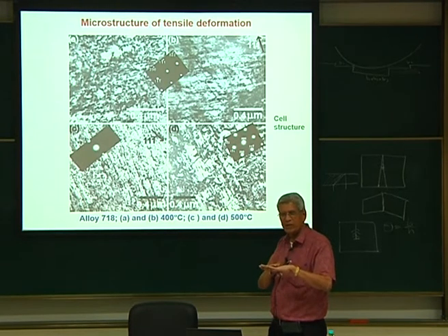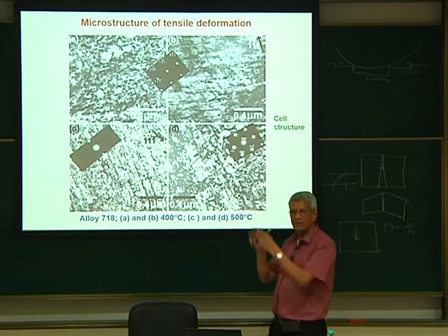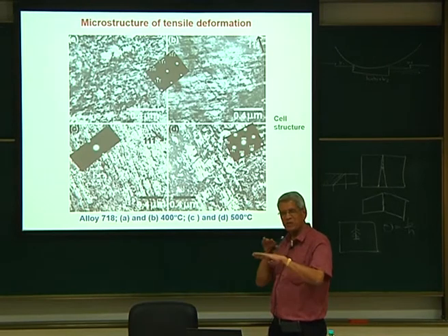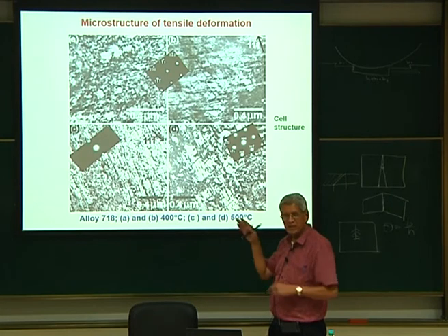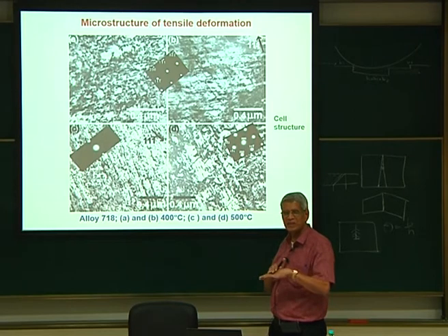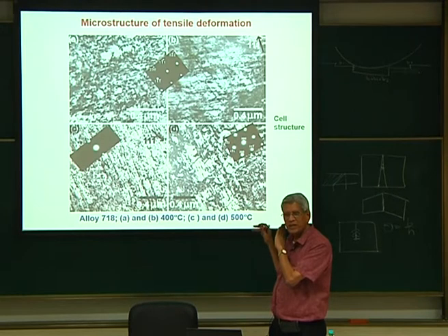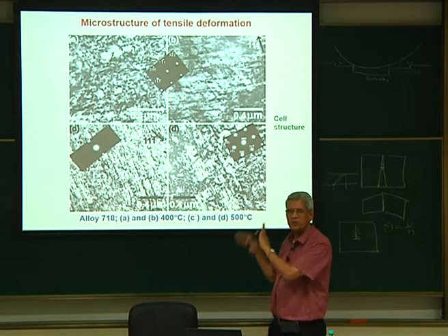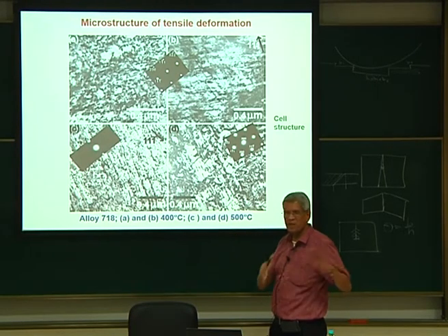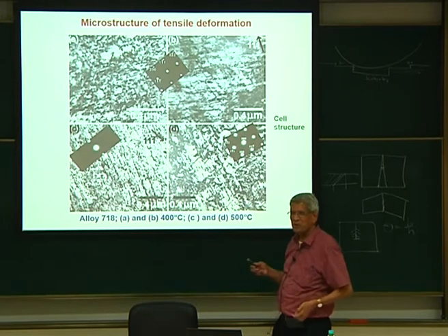If this misfit is present, we can immediately calculate, as for a coherent interface, what the misfit dislocations are, whether the separation matches with that, and whether the dislocations we are seeing have the same Burgers vector and separation, and lie on the plane which corresponds to that interface. All this information we can analyze and find out from the TEM. That has to be done. What I am showing is only the end result in some pictures, but beyond this there is a lot of analysis which has gone into producing one picture.